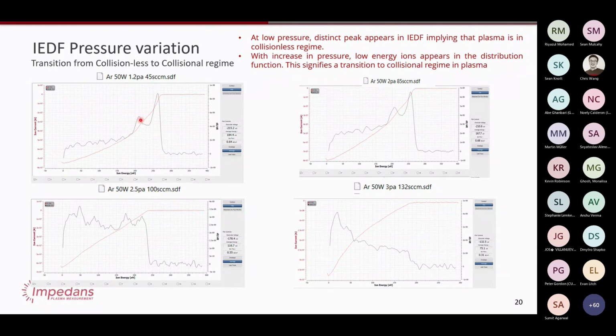So you see this peak splitting is 13.56 megahertz on the bottom electrode, and then you see this. If you look over here, there's no ions here; it's flat. But over here, it's much higher. So this is a result of collisions happening between the electrodes and so on. So you actually have this wide distribution of ions, their energy is being spread with the collisions, and then you have still two peaks available.